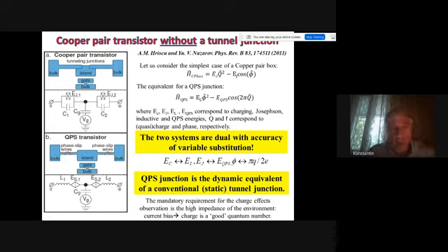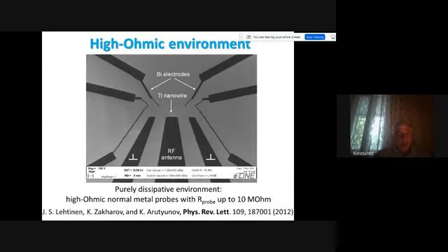Or in simple words, a conventional system with tunnel junctions has localized tunnel junctions here and here. And in our case, this phase slip effect is a dynamic equivalent of this tunnel junction. But there is one complication for experimentalists. If one wants to study fluctuations of phase, which is the quantum conjugate variable to charge, one should stabilize the charge. It's just the uncertainty principle.